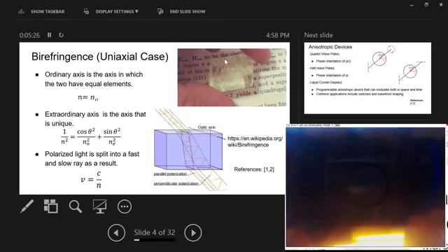So what does the dielectric tensor do to the light that's propagating in it? Essentially, it retards the phase front and slows down the light propagating through it. Polarized light consists of perpendicular and parallel components, known as the S and P polarization states.